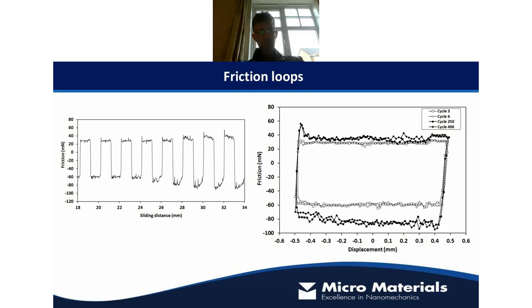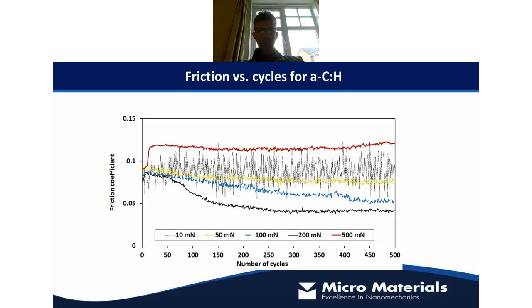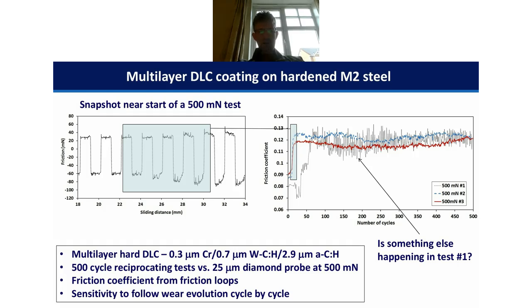So this is the raw friction versus time data, and you can see over a few cycles here, in this case, a transition to a higher friction regime. You can generate friction loops from this sort of thing. And this is typical behavior that might change as a function of load, depending on topographic influence, ploughing, transfer films, and things like this. And this one here is just a typical example of 3 different repeat tests. In one of these repeat tests, you can see that it's much more jagged